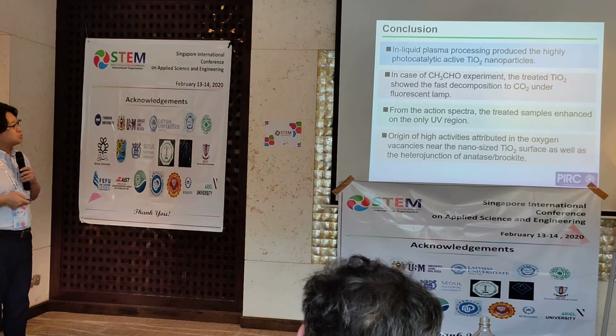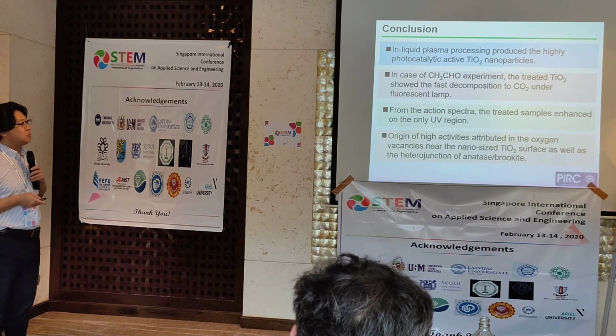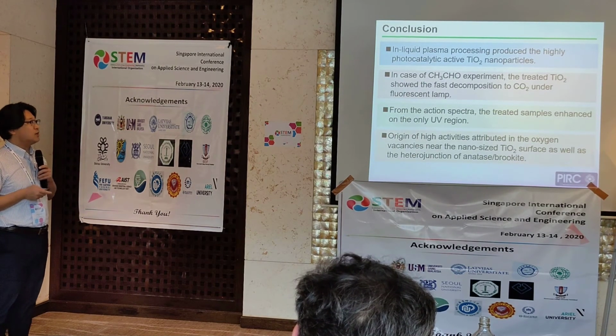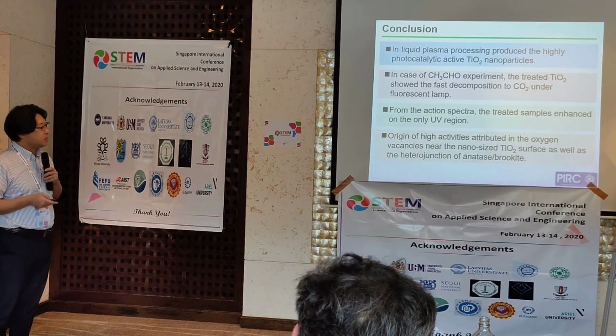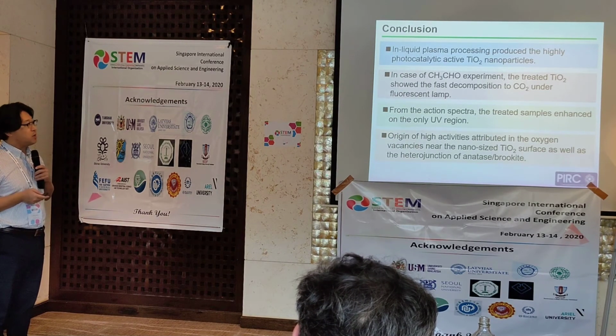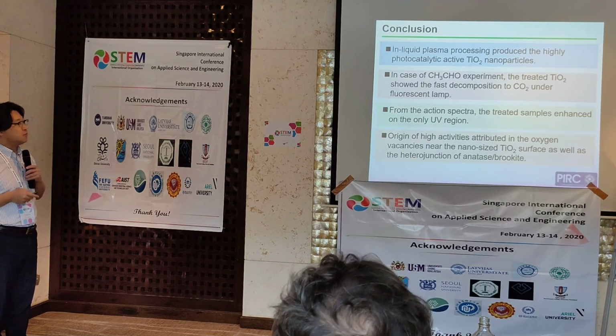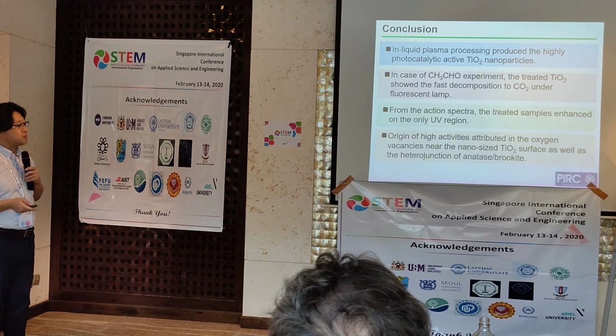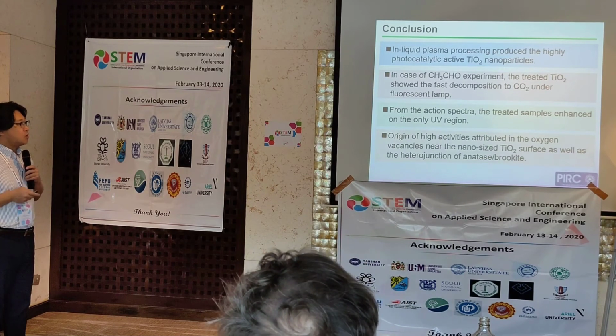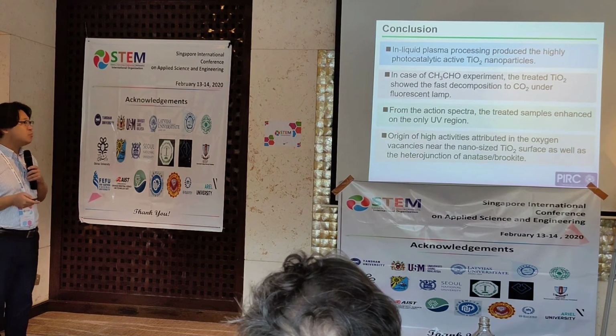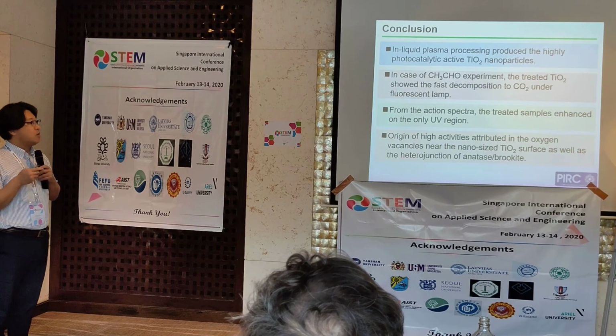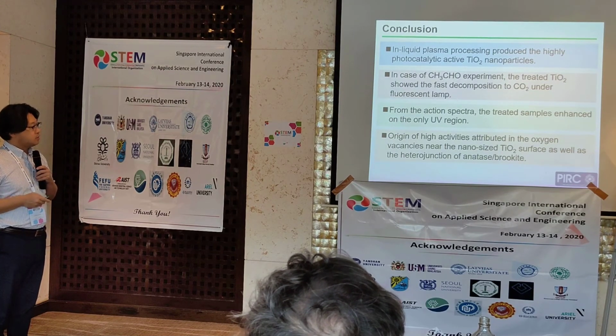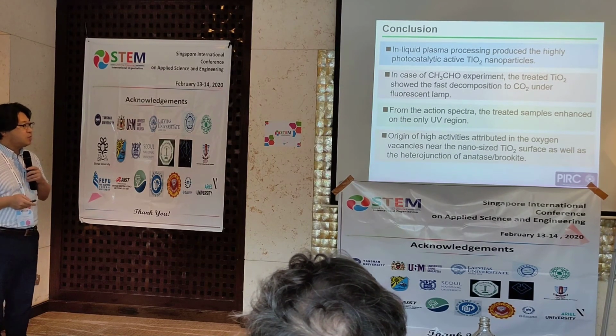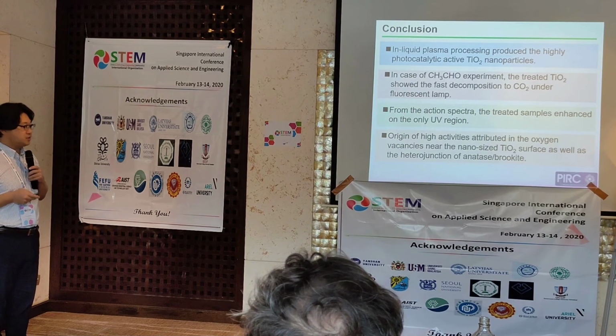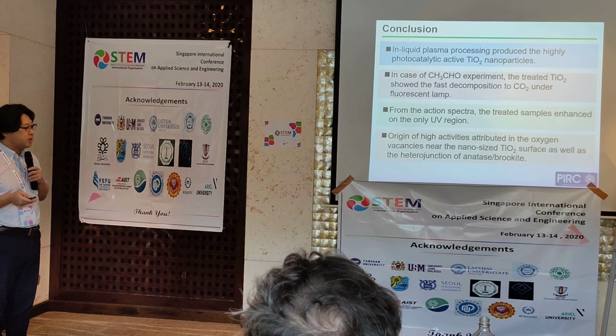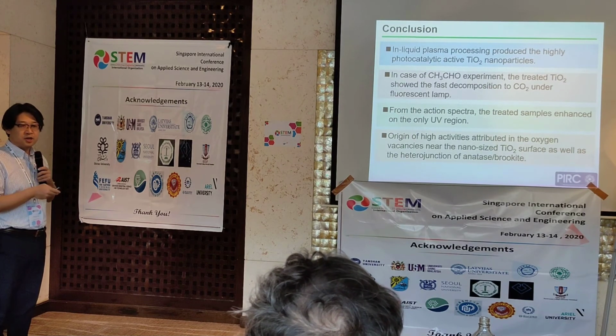So this is my conclusion. In-liquid plasma processing produced a highly photocatalytically active TiO2 nanomaterial. In the acetaldehyde experiment, the treated TiO2 shows fast decomposition to carbon dioxide under fluorescent light. From the action spectra, the treated sample is enhanced only in the UV region. Finally, the origin of the high activity is attributed to the oxygen vacancy near the surface of the nano-sized TiO2 material, as well as the heterojunction,